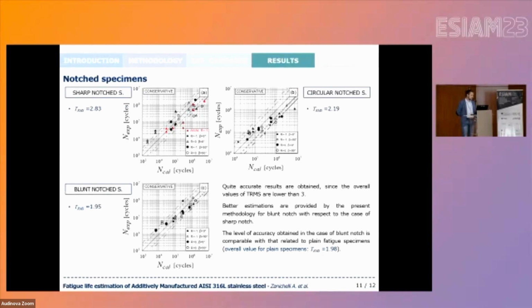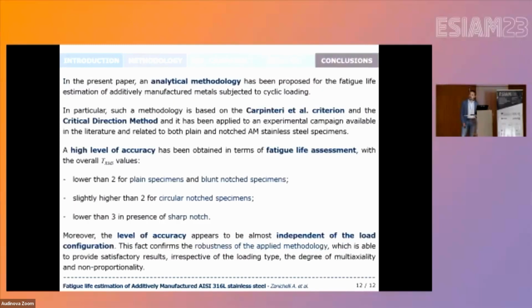So as a matter of fact, the level of accuracy that we have obtained in the case of blunt notch is exactly comparable with that related to plane fatigue specimens, which were characterized by an overall value of TRMS equal to 1.98. And now let us move to the conclusions.